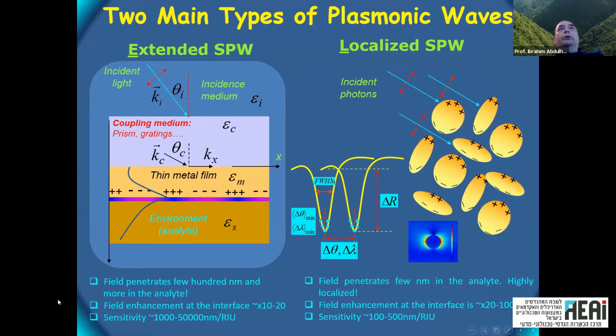Okay, so with plasmonics, we can distinguish two main plasmonic waves, the extended one and the localized one. The extended one can be excited using a coupling medium, for example, a prism or a grating, and we need a continuous film of metal. And following certain conditions, which we will be showing very soon, we will excite the wave and get this evanescent field inside the medium which we are interested to sense. The other option is using nanoparticles or nanostructures, and then the wave can be excited because the particle is kind of scattering. You get scattering from the particle, and this helps excite the surface wave.